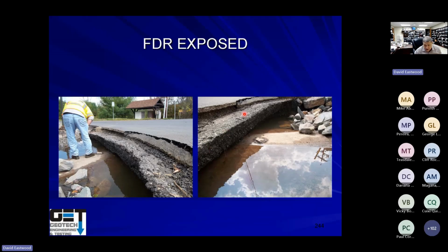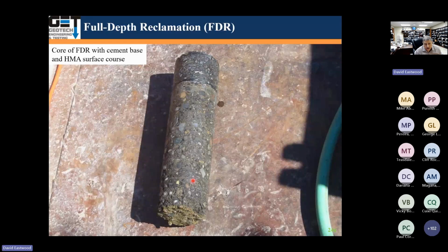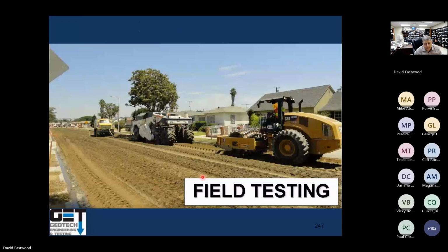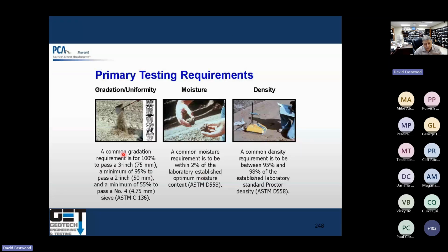Here's the stabilized layer, if you can go look at it. After it's stabilized, this is the existing asphalt and the base and subgrade mixed. That's what it looks like. That's the stabilized layer, with the asphalt on top of it. Basically, the testing that you will do is you make sure you got proper gradation, as we talked about. 100% pass the 3-inch sieve, 95% the 2-inch sieve, and 55% should pass the number 4 sieve. We check that moisture is within 2% of the optimum, and then you run density, 98%, ASTM D558.